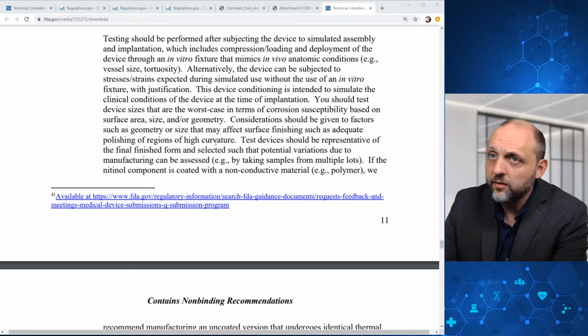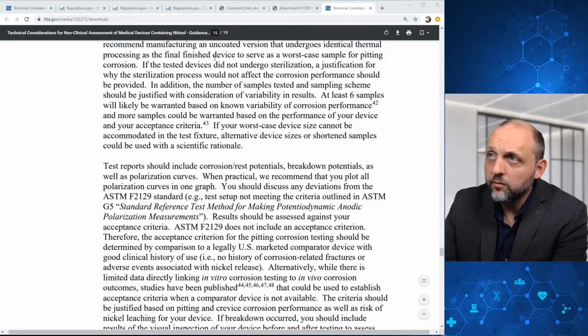And consideration should be given to factors such as geometry or size that may affect surface finishing. And test devices should be representative of the final finished form. And FDA recommends manufacturing an uncoated version for coated devices that undergo identical processing. If the tested device did not undergo sterilization, a justification for why should be provided. And in addition, the number of samples tested and sampling scheme should be justified with consideration of variability in results. FDA says at least 6 samples will likely be warranted based on known variability. That's a minimum, not a recommended sample size.